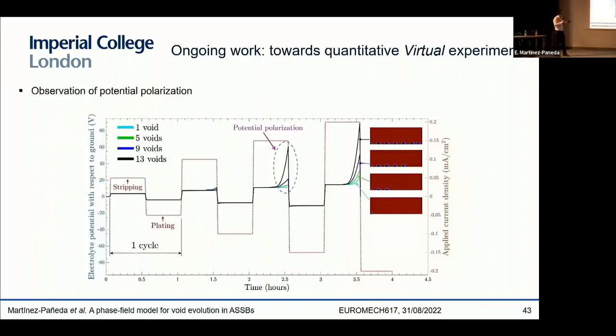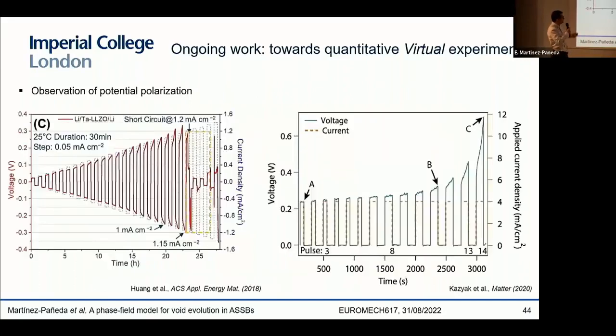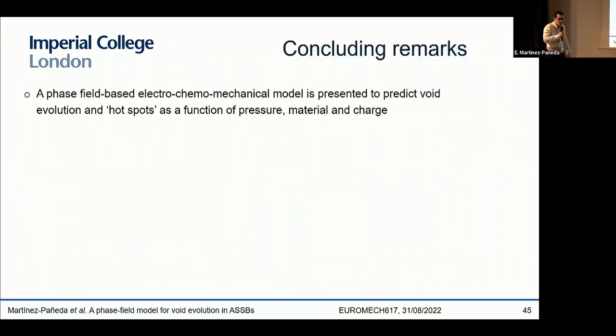And one of the things that you can see is, of course, that you can measure the potential polarization. So you can apply a current and measure the voltage over multiple cycles of charge and discharge. And you can see how you get this potential polarization, this increase in voltage that you see in the experiments, as the surface integrity becomes more and more degraded, either because you have many voids or multiple voids that are growing and interacting with each other. And this is essentially what you see qualitatively in the experiments, as we have discussed, and some of you showed yesterday. So let me just conclude, hopefully in time for a few questions.